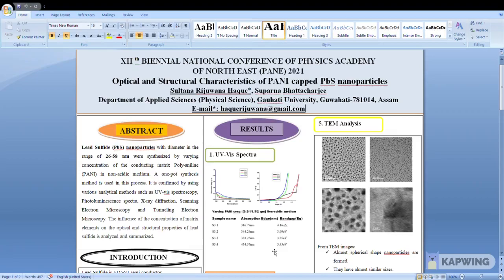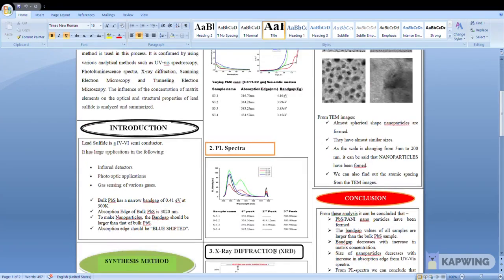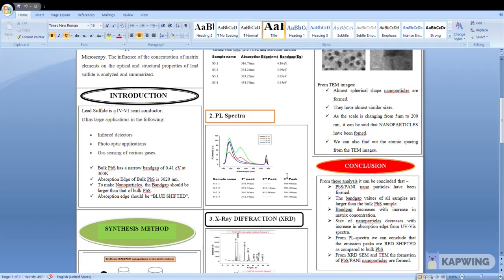In PL spectra, you can see that the peaks are in the range from 338 nanometer to 586 nanometer. By increasing the matrix concentration, the PL intensity increases and it indicates more excitonic recombinations.